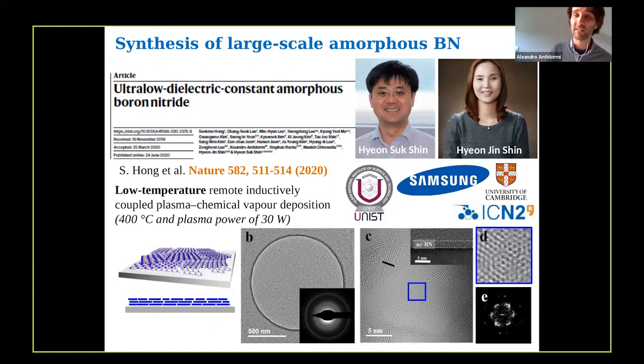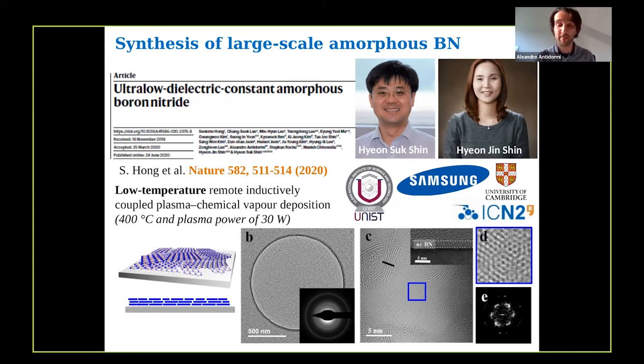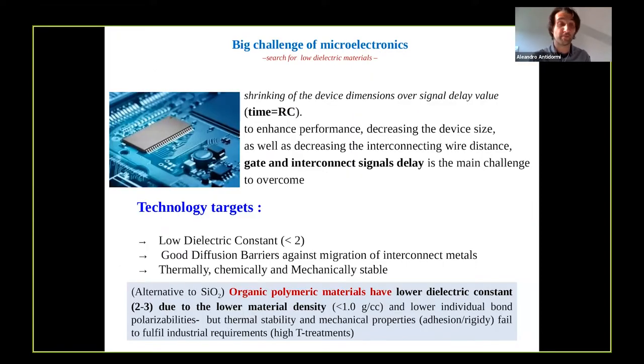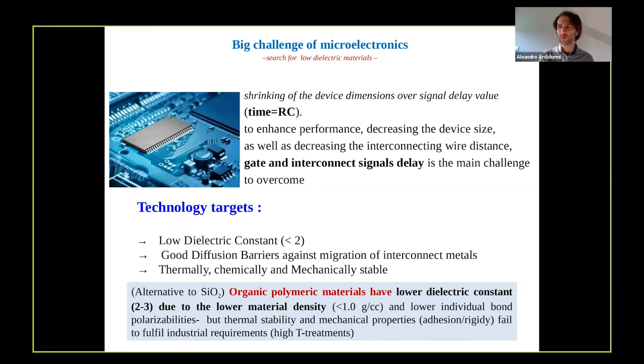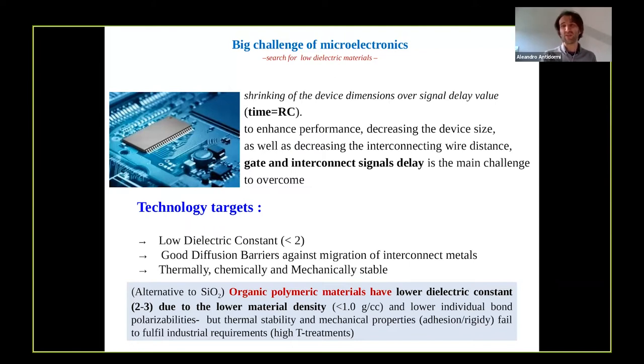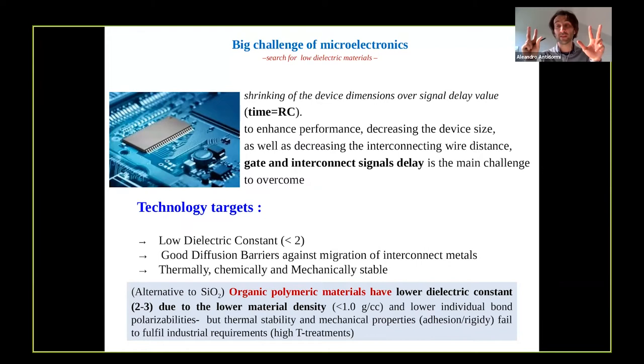In particular, this is a solution to a very long-standing problem: in order to reduce the size of integrated circuits, one looks for very good dielectrics with a very low dielectric constant, but thermally and mechanically stable, to separate the metallic vias in integrated circuits. Many materials have been proposed over the years, but many were not thermally stable. Some tried to decrease the dielectric constant by making the material porous, but that is not a suitable solution. Amorphous boronitride seems to be the right candidate for this kind of application.